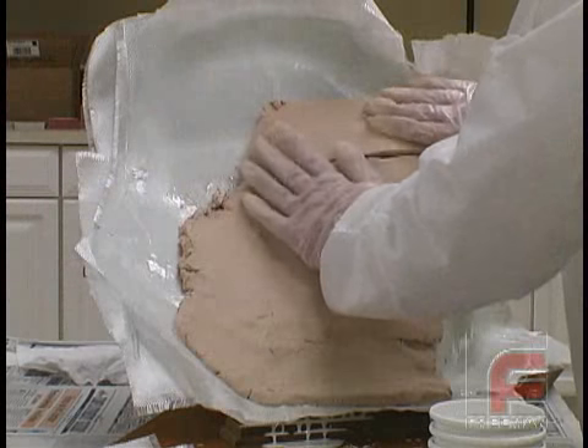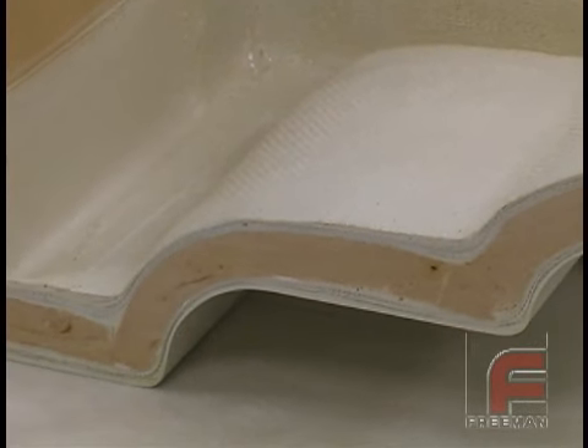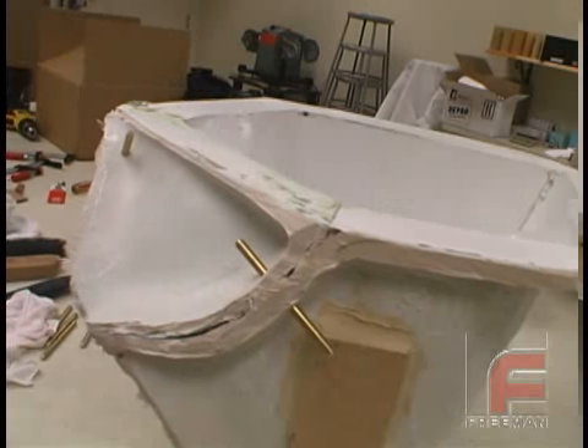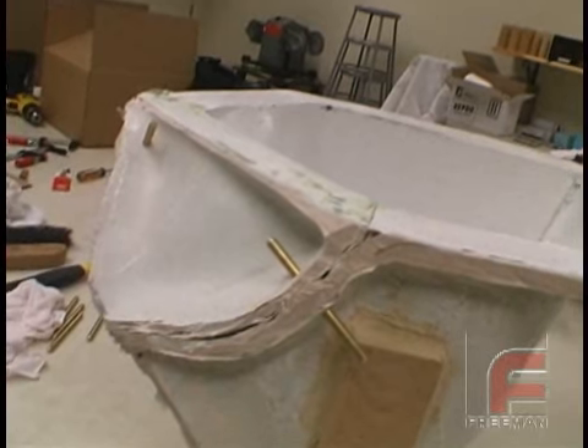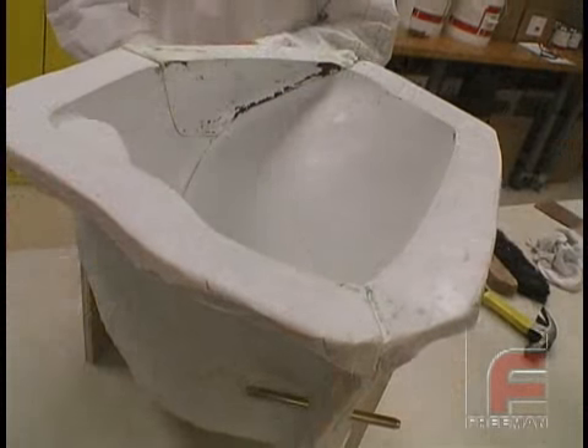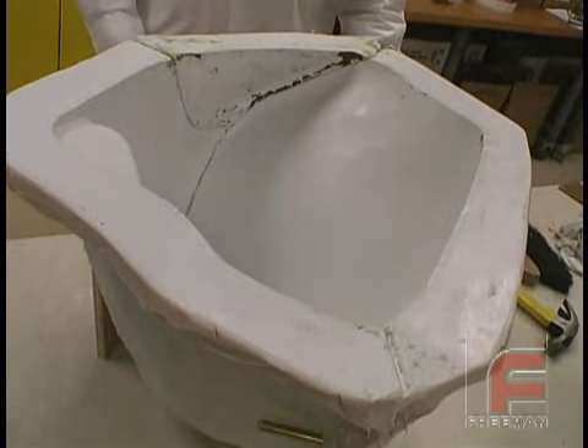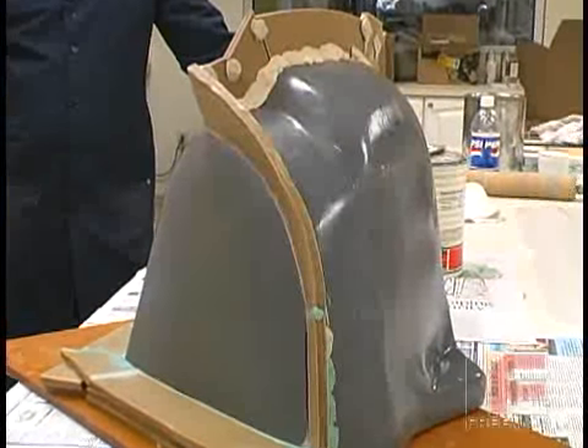In this process, you apply a half-inch thick layer of paste laminate material between layers of fiberglass cloth, creating a very strong yet lightweight tool in much less time. This project is going to be a three-part mold with curved parting lines. To form the parting lines, we're using Freeman's 3/8 inch thick, high temperature sheet wax.